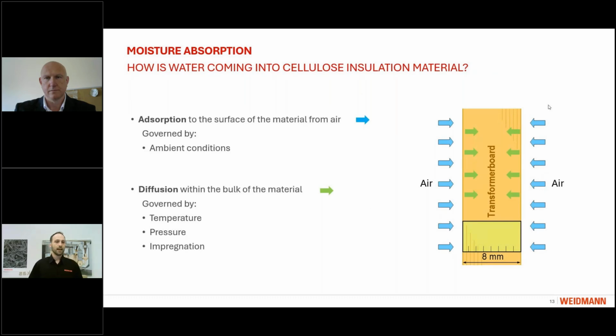Now, you might think that we have a little typo in the word absorption, but actually that's not the case. So when we talk about moisture absorption overall, we mean just water going into the board. However, this process in nature is separated into two processes. On the one hand, there is adsorption of the humidity in the environment to the surface of the board. And secondly, we have diffusion of that humidity into the board. Both of these are governed by temperature because many natural processes, if not all of them, are governed by temperature. But the adsorption is also very much defined by the ambient conditions, while the diffusion depends also on the pressure the material is within and whether or not the material is oil impregnated. We will see later what the influence of such an oil impregnation looks like.